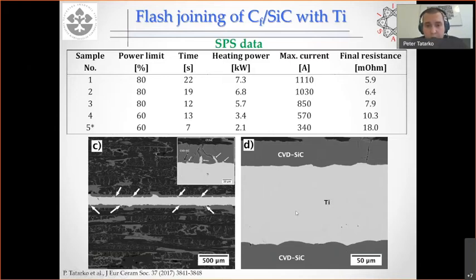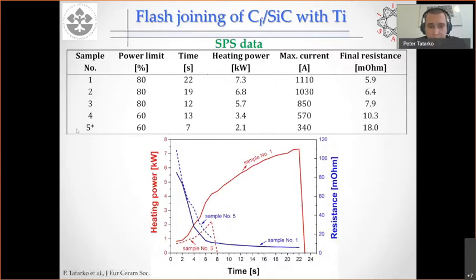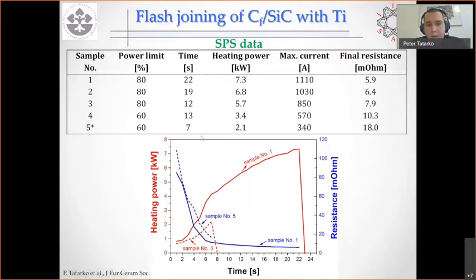So it was very different than in the other case. So what happened if we compare the first sample with the highest heating power and the last sample with the lowest heating power, you can see the resistance of the sample in the blue line, there is actually no effect, it drops very, very similarly. But then the heating power for sample number 1 with the highest heating power, you see it continuously increasing until around 7 kilowatts.